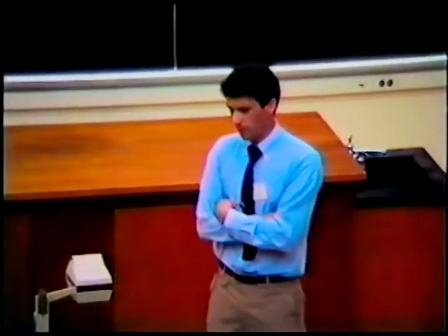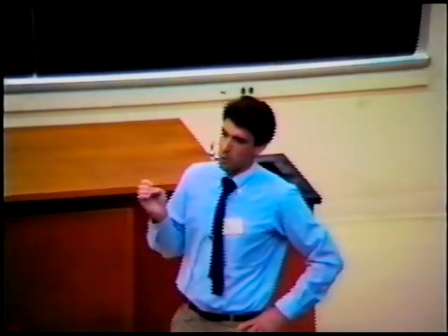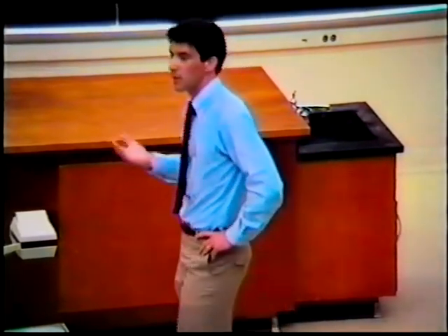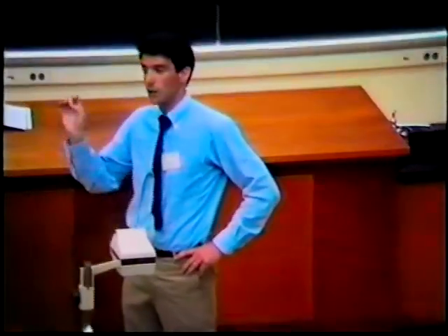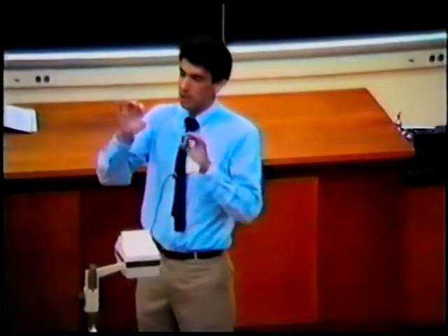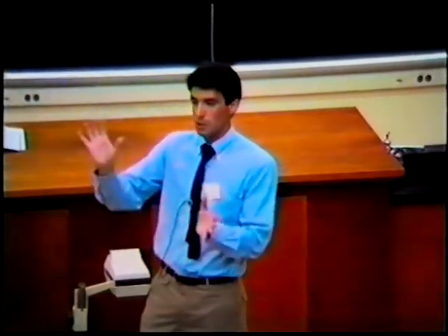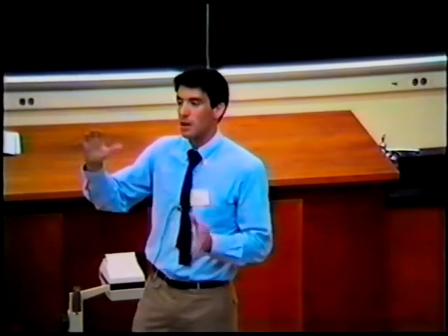I don't think that's the point of my work, though, because the entrance of the cavity will affect the Henry's law constant. That's the way one particle gets into the cavity. And my concern was that I take the Henry's law constant as an input to the model. This is just adapting Soto and Meyer's calculations for the Henry's constant, and they took that into account to obtain their potential energy curves for the molecule-surface interaction. So once the molecules are inside the cavity, the only geometric parameter that matters is the size of the cavity.